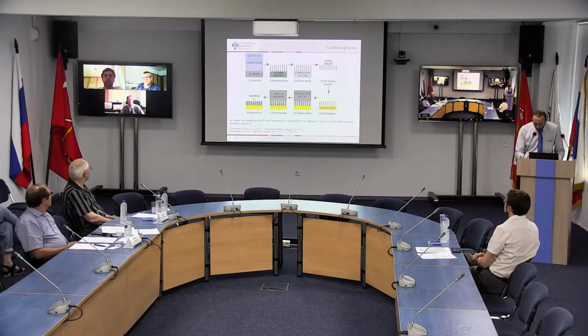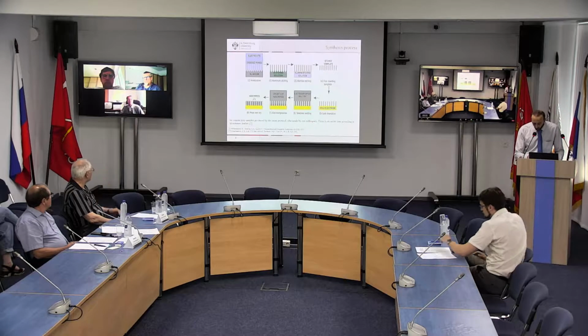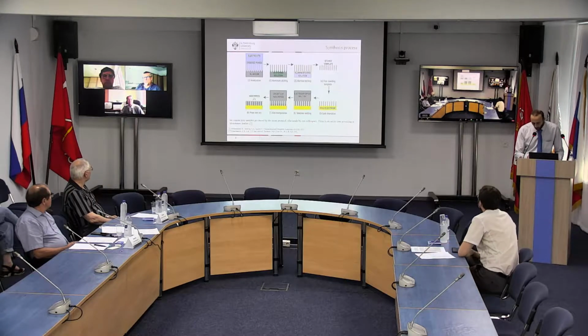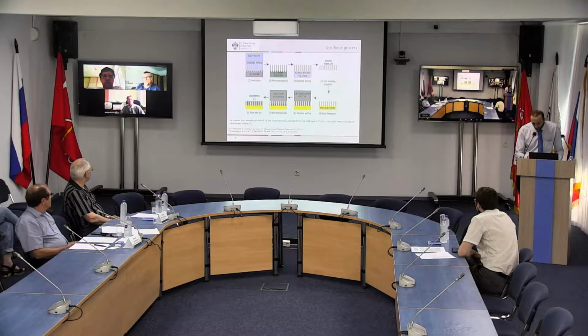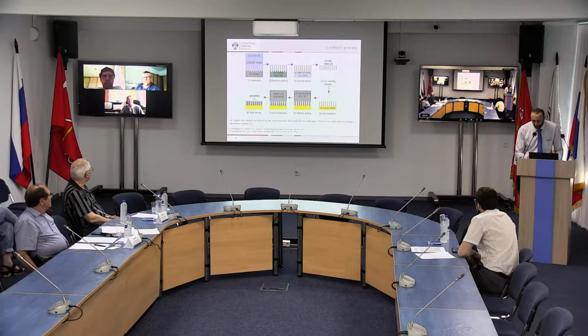Here we can see the synthesis procedure where iron is deposited into a prepared porous aluminum template, where I would like to mention that synthesis was done by our colleagues at Moscow State University. They also performed a Mossbauer spectroscopy study for similar iron nanowires by the same protocol, and they showed absence of an oxidized phase.